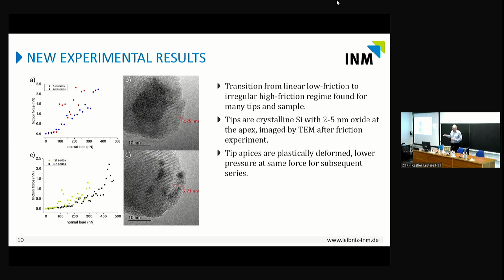The longer you do this, the higher the force at which you get the transition to this high friction regime. The high friction regime is very scattered. It's going up and down, sometimes very high, sometimes not so high. This is very unpredictable. But when we go back, we go into this low friction linear regime again. So that is all reproducible.